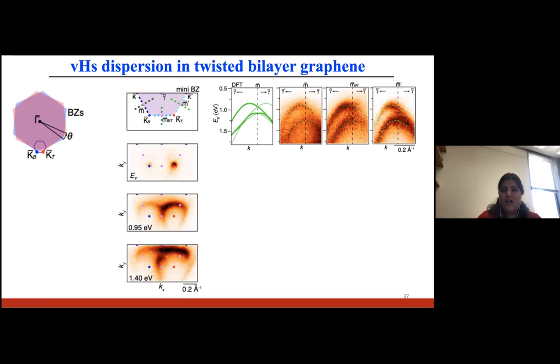And so next, what we can do is look at the dispersion along these directions: gamma M_BT, gamma M prime, and gamma M. And this is what I'm showing here. And as you can see, we observe downward curving bands, which match the DFT calculations pretty much.